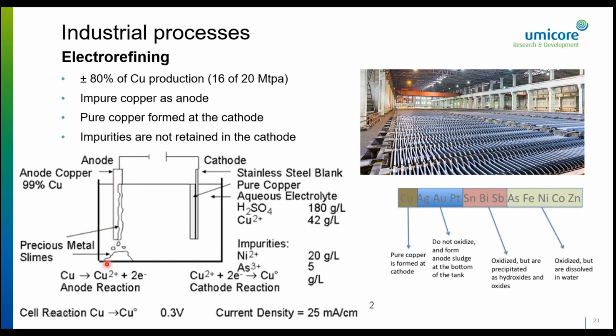So here you have an impure anode. There are a lot of impurities present in the anode, and you can selectively extract the metal and deposit it on the cathode. So this is a way to purify your metal. This is applied a lot, and you get a very pure copper. The impurities all have different behavior. Some will not dissolve, others will dissolve and precipitate, others will stay in solution. But it's only copper that will deposit on the cathodes.